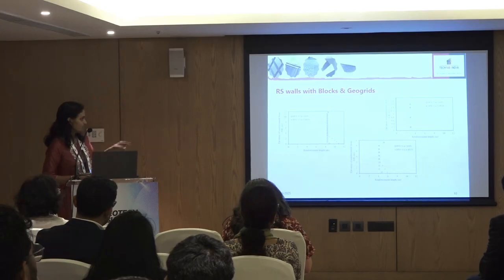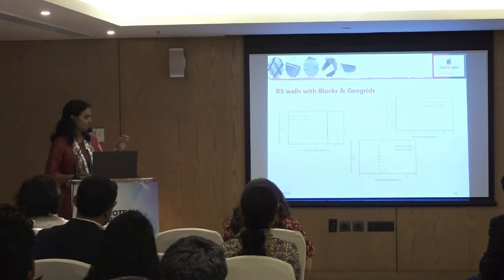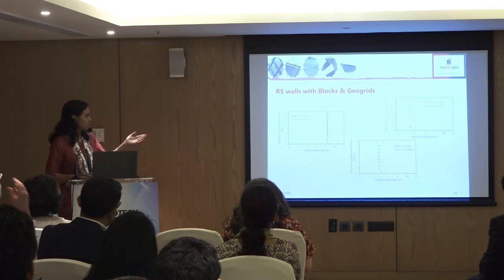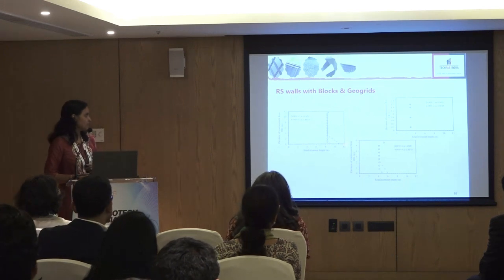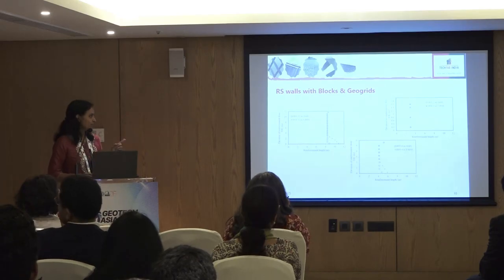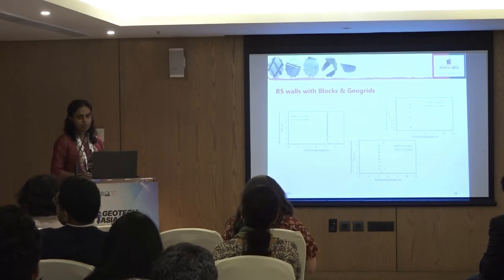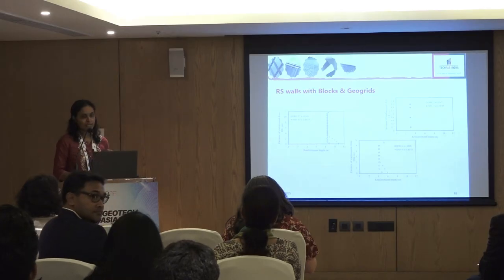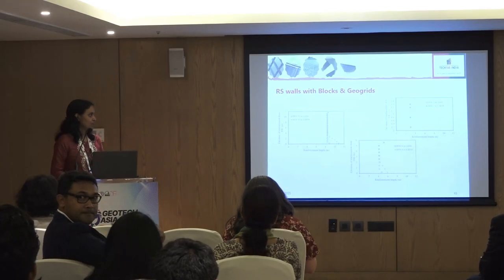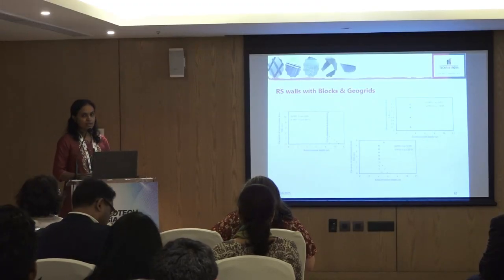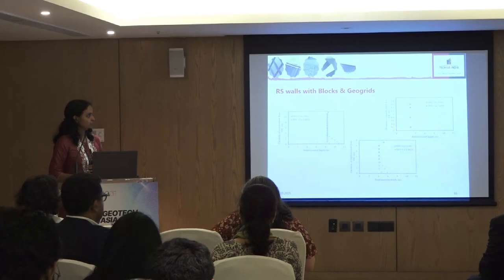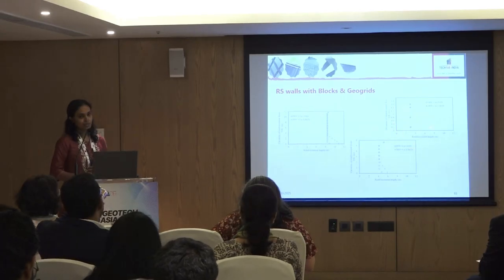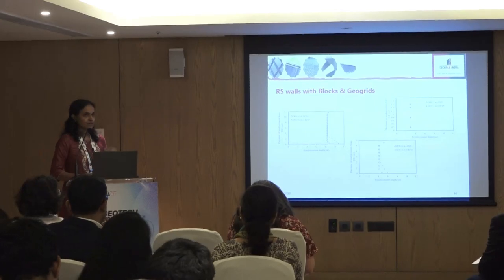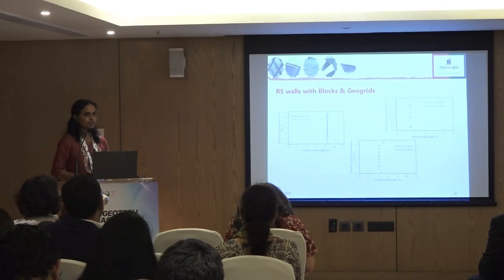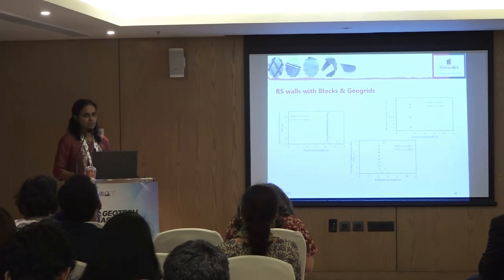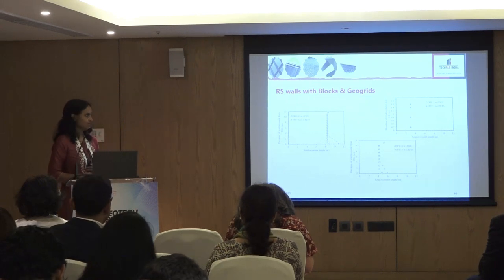So from this, the circle shows the design length from ASD method, and the cross shows the design length from LRFD method. So we can see that for higher heights of the walls, the LRFD is demanding more length towards the bottom of the wall. And for very small heights, both the methods are recommending almost the same lengths for the geogrids. And on geogrid strength, both the methods are demanding almost the same strength.